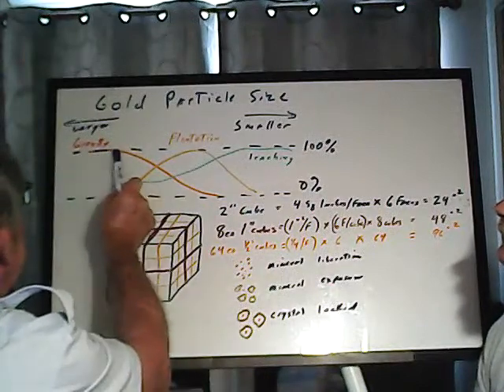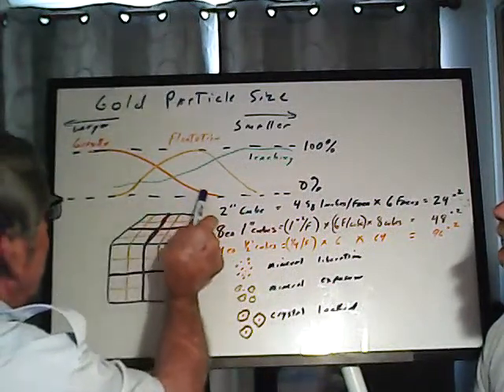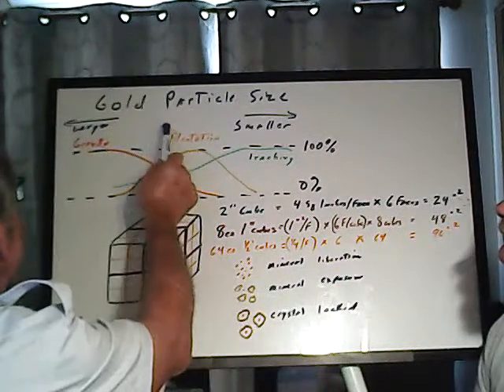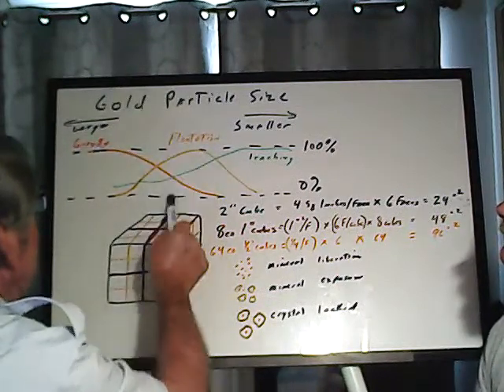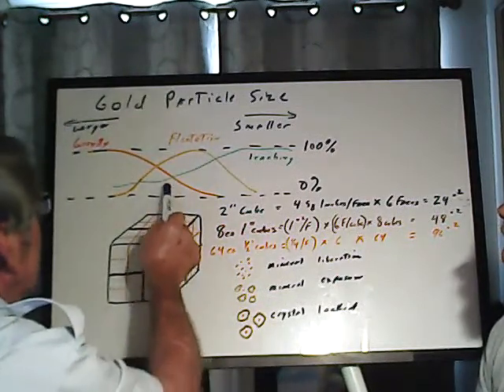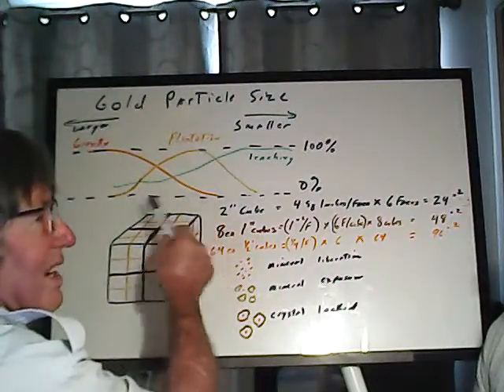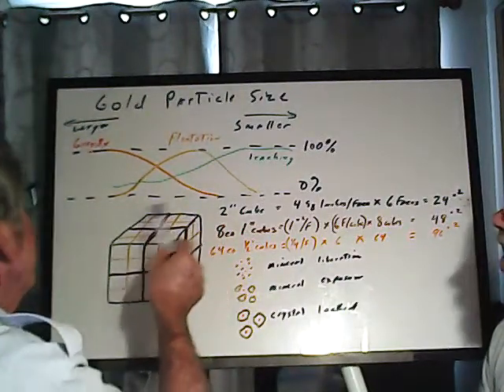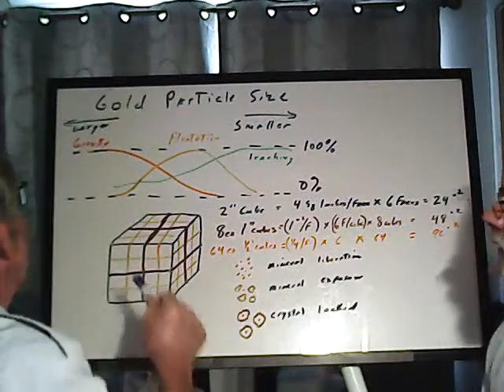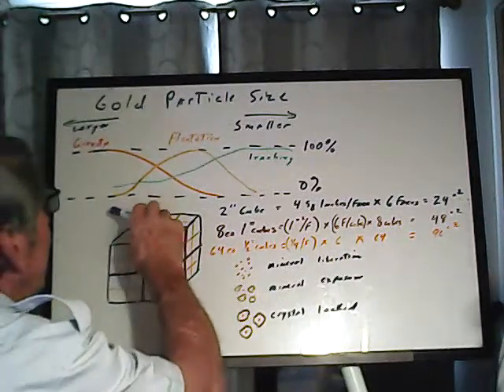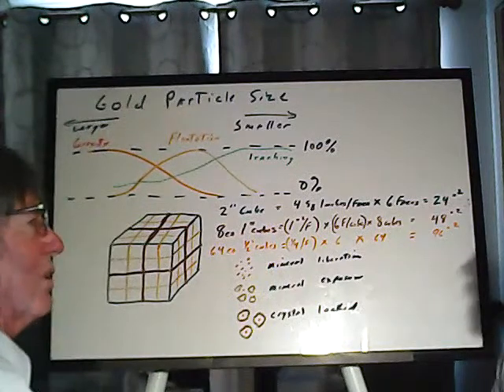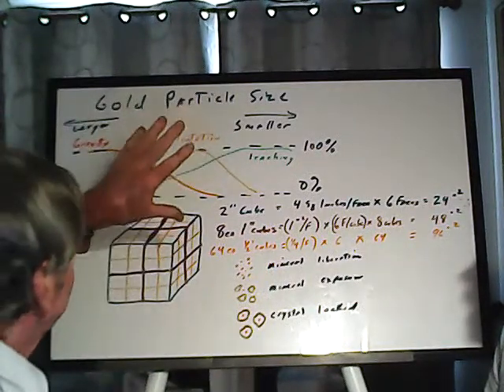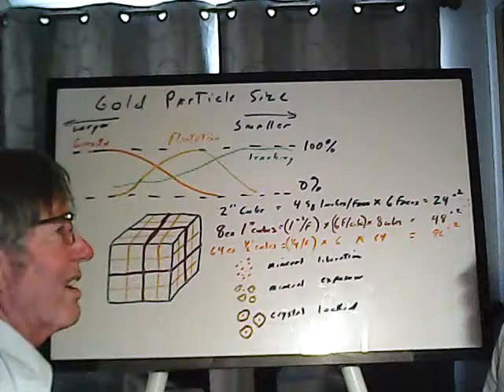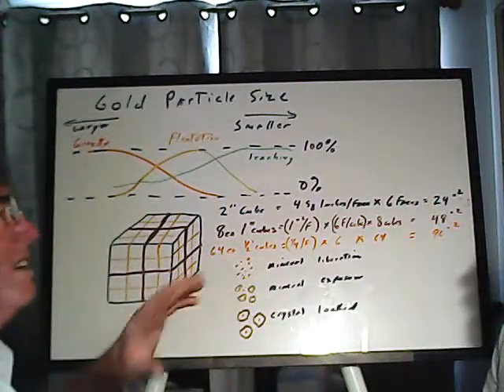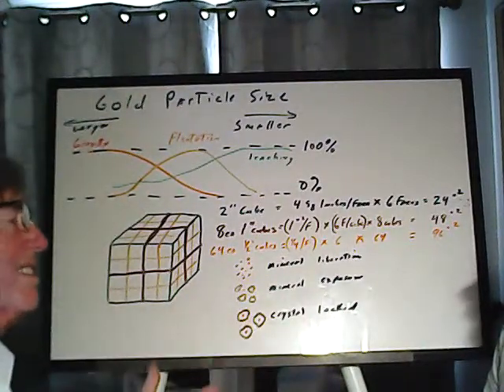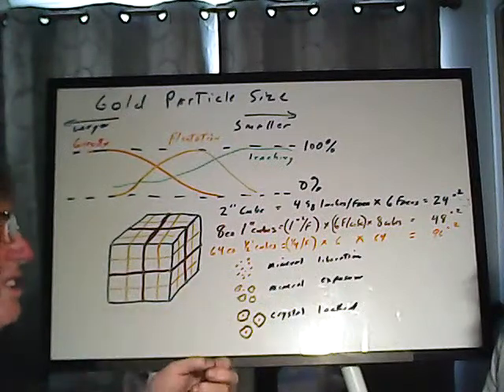Now, as the particles get smaller, your recovery gets worse and worse. Somewhere around 100 mesh would be about here. That's where you really start to lose in gravity separations. Up until then, you should get almost 100% recovery. Correct. Now, another way of recovering the gold is used almost exclusively in hard rock. It's also used for a vast variety of other minerals. It's a very versatile technique called flotation.